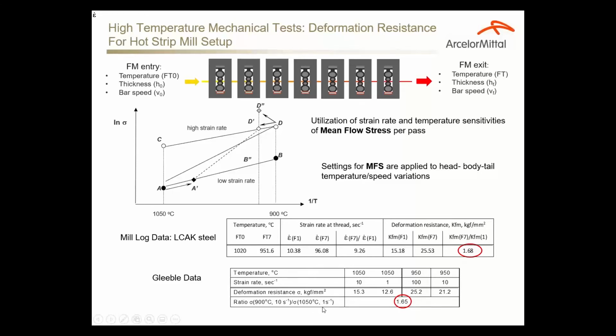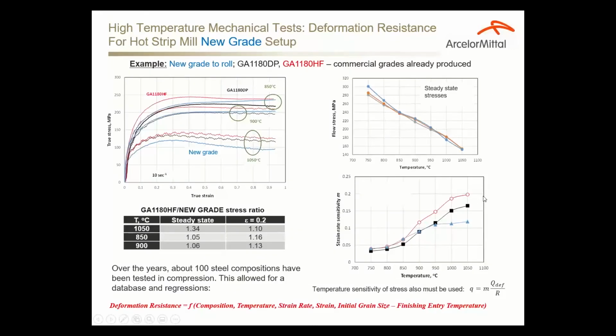This ratio that we obtained in Gleeble by extrapolation is pretty close with what mill model calculates during rolling. So based on this, we were very confident that we could provide the information using just this simple 4-point test. With the sensitivities, we can actually modify temperatures and strain rates and adjust the numbers for any entry-exit combination of temperatures and speed.